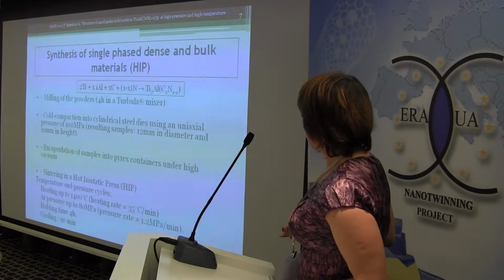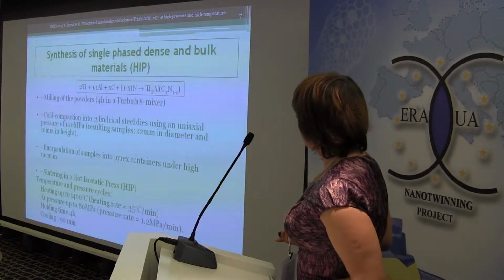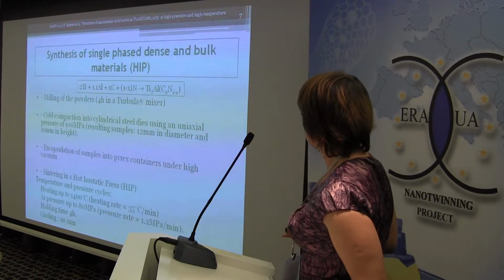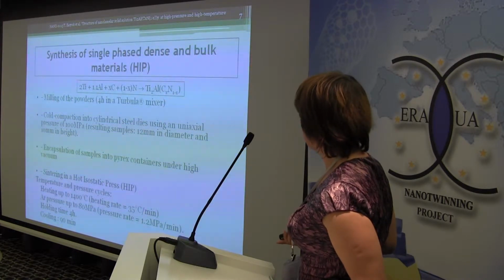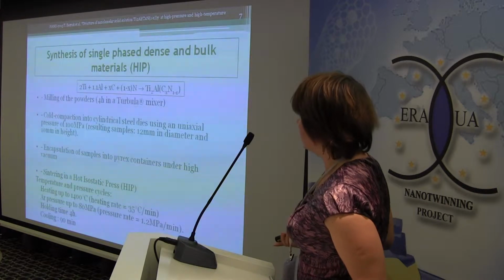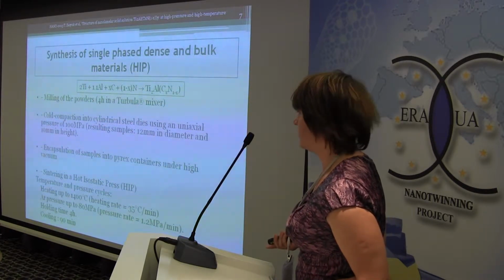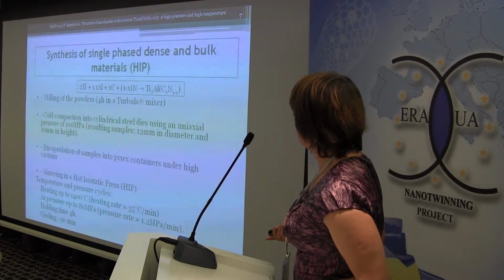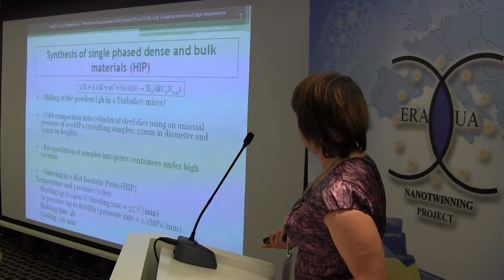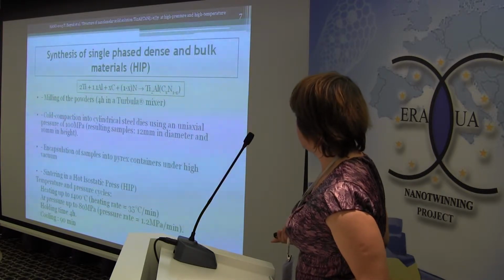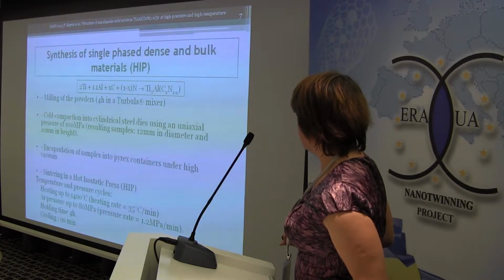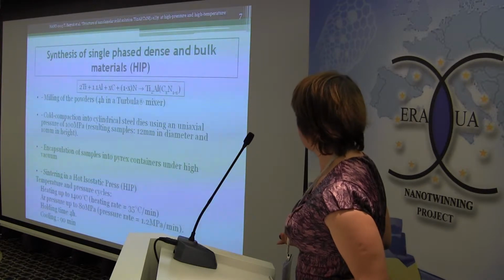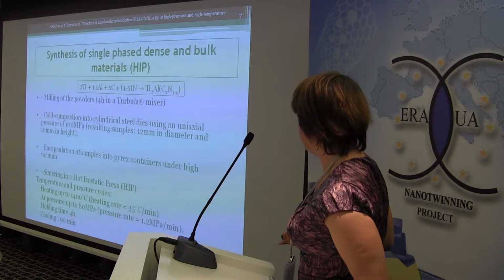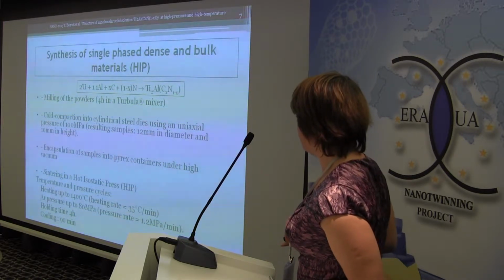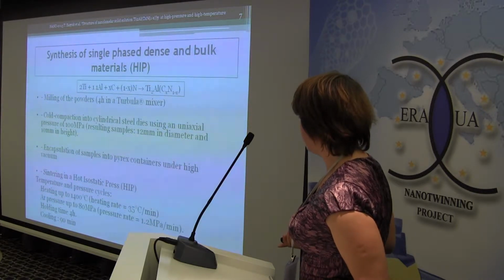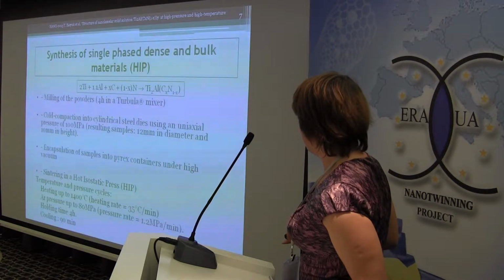For our work, we synthesized bulk materials of the solid solution using the hot isostatic pressing technique. As initial compounds for synthesis, titanium, aluminium, aluminium nitride, and titanium carbide powders were used. They were mixed for 4 hours, pressed into pellets, and encapsulated into Pyrex containers under high vacuum. Then the synthesis was performed for 4 hours at a temperature of 1400 degrees and a pressure of 80 megapascal.